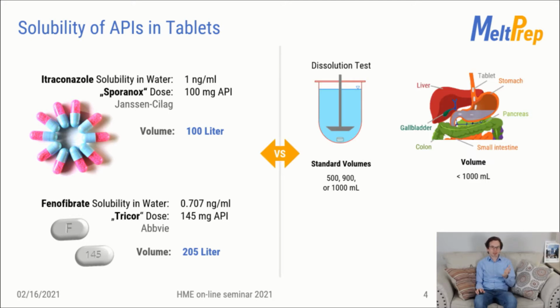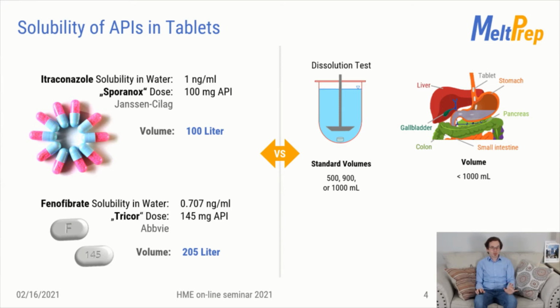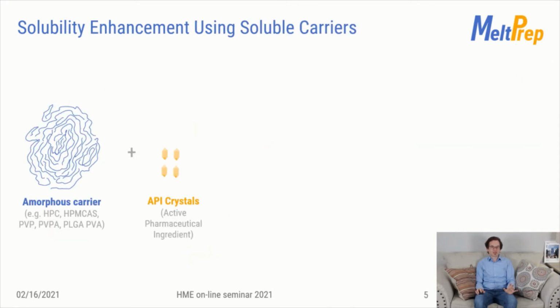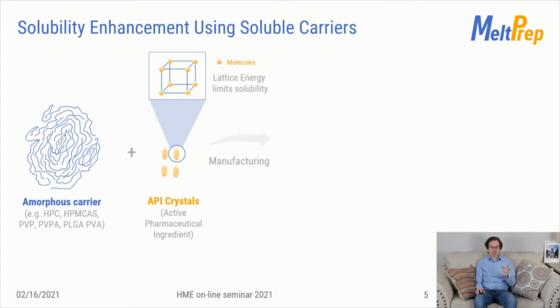So what's the trick? How can we dissolve enough API in our GI tract to make it accessible for the body? As with every trick, one has to understand the basics before we can unfold the magic. Very often, it's the lattice energy of a crystal that holds the molecules together and prevents dissolution. By processing the crystals with an amorphous carrier via hot melt extrusion, we can produce solid dispersions with reduced lattice energy and increased solubility. Different types are possible.